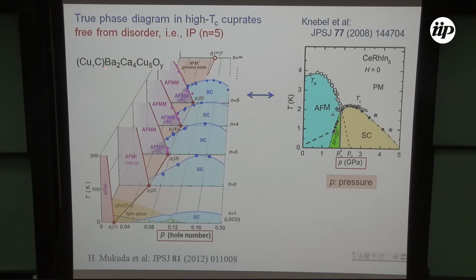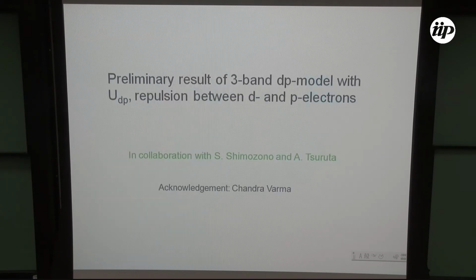obtained. For example, in this case, n equals 5 and the inner layer, this phase diagram as a function of doping rate is like this. So the antiferromagnetic phase extends to rather high doping, and there is a coexistent region of antiferromagnetism and superconductivity, which is very similar to CeRhIn5. So this is pressure, this is hole number, both P, but it's different, of course. So this at least suggests to us that also in high-Tc cuprates, the charge transfer plays some crucial role.